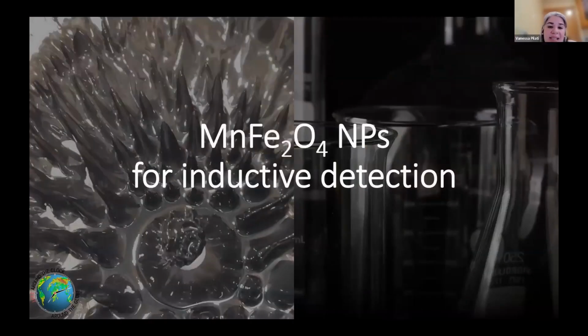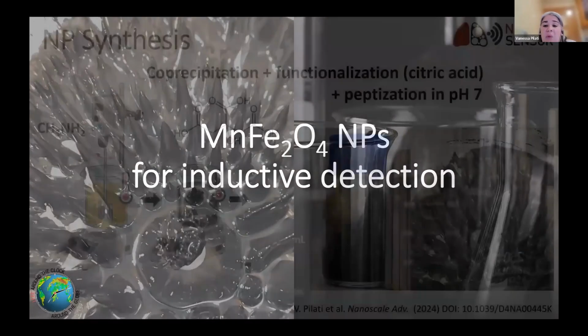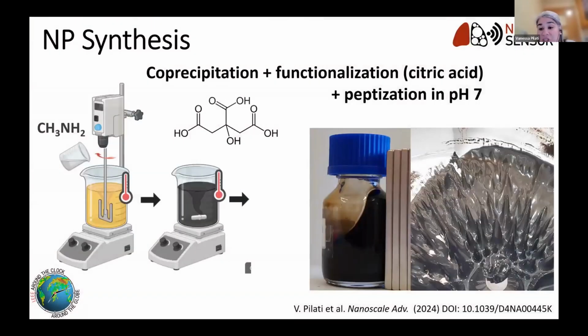So in this work, we synthesized manganese ferrite nanoparticles, and we investigated their efficiency for inductive detection. We used the co-precipitation technique and functionalized the nanoparticles with citric acid to provide carboxyl groups at the nanoparticle surface to further conjugate to antibodies and proteins.